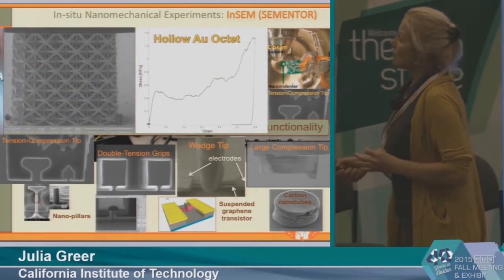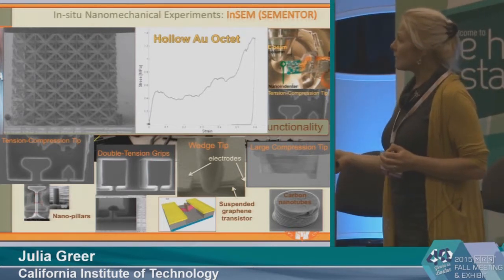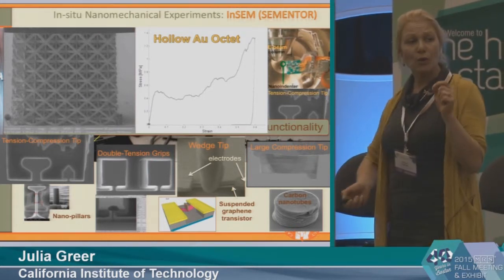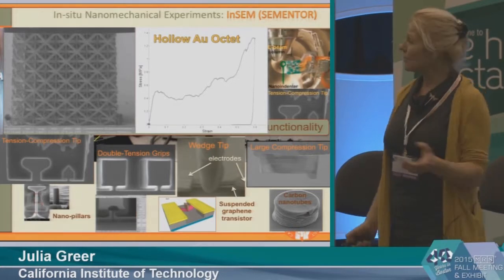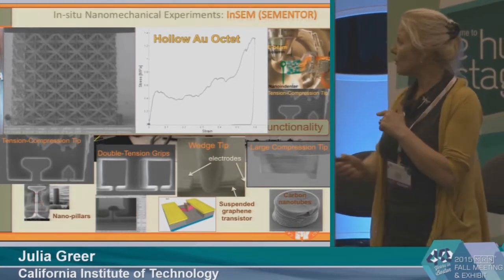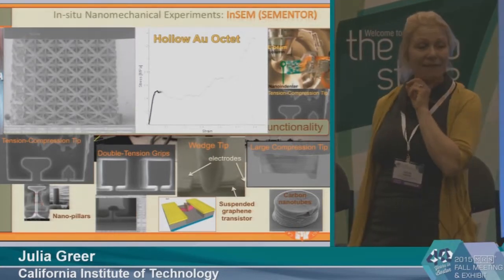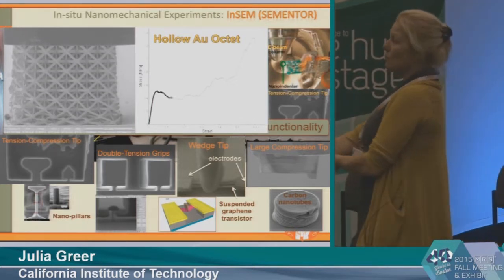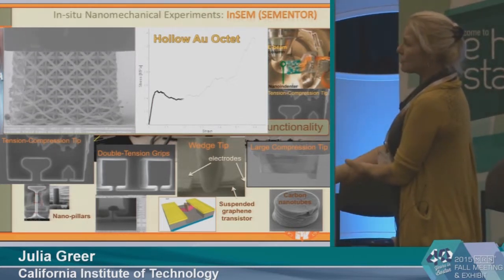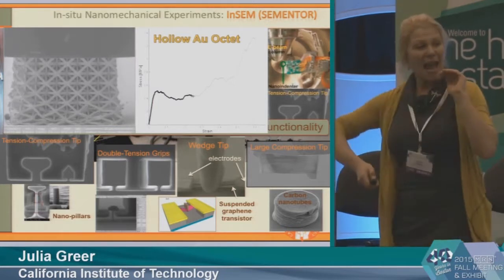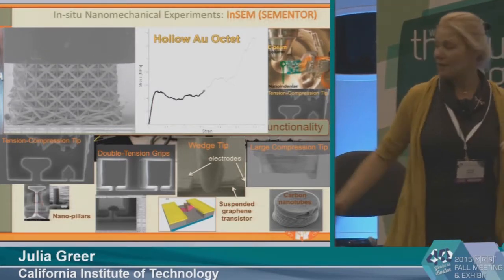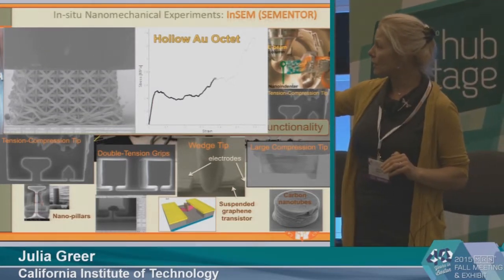And here's an example. So my former student, Lauren, did this particular experiment. So this is a hollow gold nanolattice, and she's going to compress it. And now, what we have is both the data and the accompanying video, and what you can start to notice right away, for example, is that the material starts deforming only at the interface with the substrate. And this part of the material doesn't even know that it's being compressed.